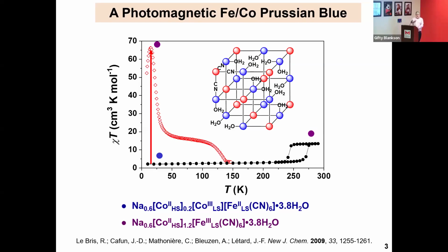This large enhancement is different than molecules in that below 19 Kelvin, this material undergoes long-range magnetic order. In other words, if you had a really cold refrigerator, it would stick to it. Right? Above 19 Kelvin, you have too much thermal energy. This long-range magnetic order goes away, and now you have paramagnetic spin centers. Those paramagnetic centers are uncoupled because there's too much thermal energy for them to spin pair. And then if you increase the temperature further, this collapses down to a diamagnetic state where you've gone back to low spin cobalt-3 and low spin iron-2, no unpaired electron.